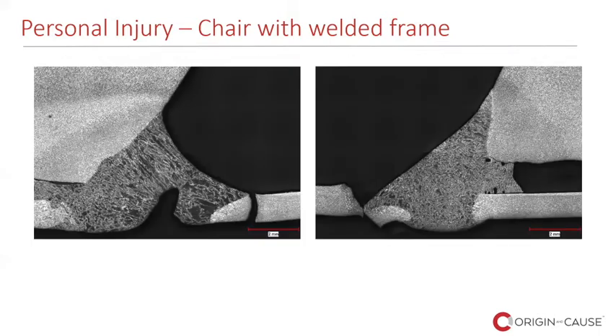We also conducted a metallurgical evaluation of the weld. The darker constituent in the middle is the actual weld. The lighter constituent in the image is actually the frame and the bar. You can see that the weld is non-uniform and it has some pores in it.